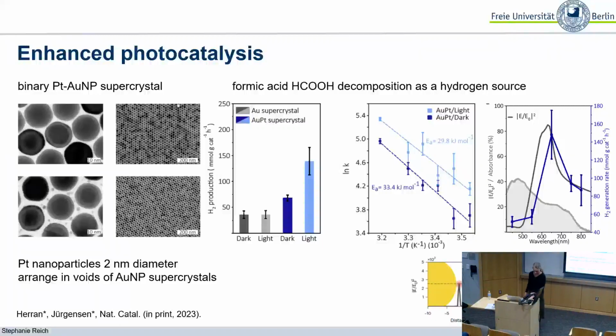I mean, one thing that's shown here that I haven't spoken about is a dependence of the catalytic activity on wavelength. These points here are measurements of the reaction rate as a function of wavelength, and that is compared with the calculated enhancement of the electric field inside the supercrystal. And you can see that it very nicely follows the field enhancement that you see inside these gold nanoparticle supercrystals.